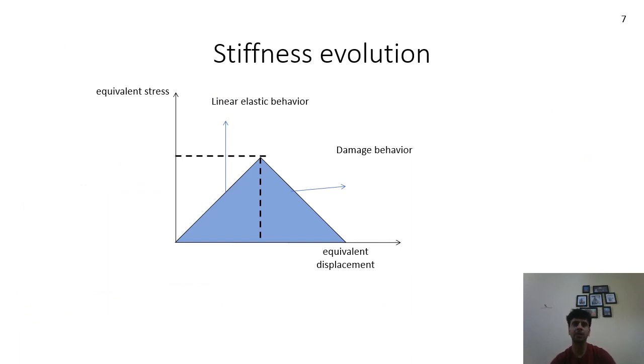And how is the value of d calculated? The value of d is calculated by assuming that the stress strain behavior of my material is bilinear, which looks like this. The point of inflection is your maximum stress point, which is input, and after that the curve starts going down in a linear manner. The area of this curve is the fracture energy input that you have already provided.